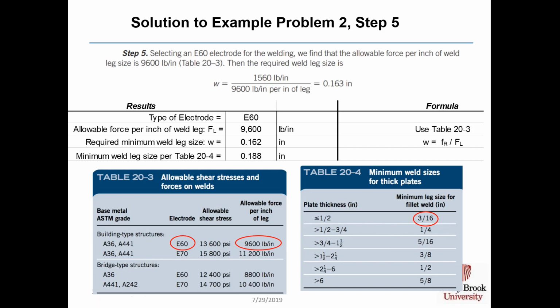We take our 1560 pounds per inch, which was small f, I called it 1559, and we divide by the 9,600 pounds per inch to get 0.163 inches. That's this step here in the spreadsheet. I called it 0.162. But it doesn't matter, the small difference, because we have to round up anyway to 0.188 inches, because that's what table 20-4 is telling us to do for a plate that's half an inch thick.